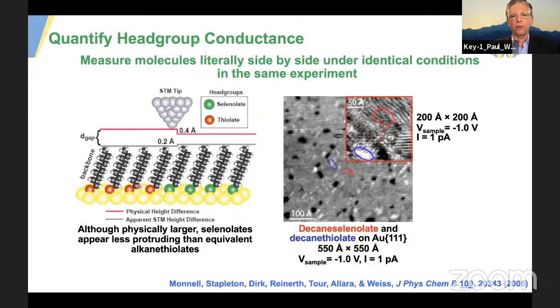And so for gold, there was an argument over whether the sulfur or selenium, which are in the same column of the periodic table, would be a better contact. Some groups said that the selenium would be 5 times more conductive, and other groups said the sulfur would be 5 times more conductive. And there were measurements, there were predictions, theoretical predictions, everywhere in between.